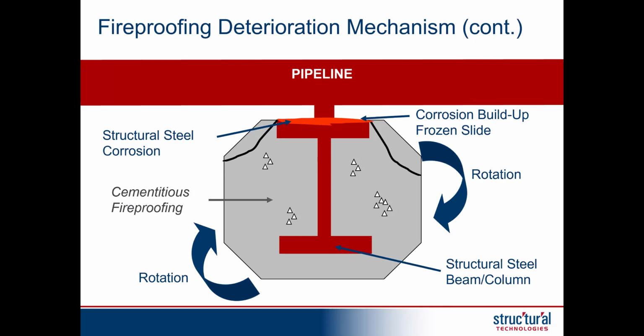Unfortunately, these pipes would move in and out with process streams, and unfortunately it corroded and seized up. It started galling, and because of that it froze, and then it started rotating the concrete, and we started having breakage on both sides. We had to understand the root cause, and the root cause was the seizing up, so we came up with a new system to put a half-round steel bar and then have the pipe shoe run on top of that half-round instead of fully flat on that embedded steel beam. But it becomes a big problem, and we see this quite frequently in older refineries and chemical plants where they have the steel beams with the flange exposed. As you can imagine, that exposed flange is also subject to atmospheric corrosion.